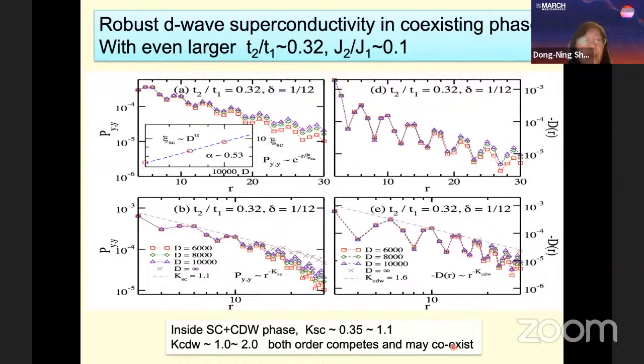This plot shows another point where T2 over T1 is much larger than the ones we used before—around 0.32. We find that the superconductivity still decays power-wise, but this power exponent is increased to around 1. So within the third phase, the superconducting correlation may vary, but it remains a power law decay.